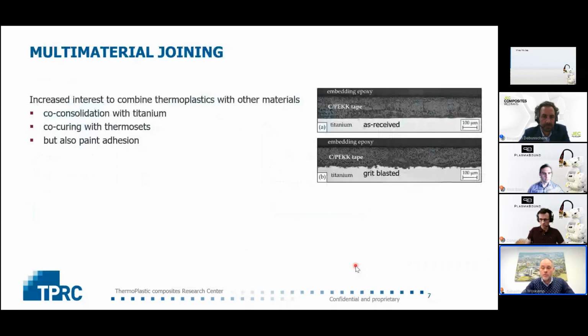So we have run 2 PhD projects already on the joining of thermoplastic composites to titanium, specifically carbon PEKK, through co-consolidation. So in one step, without a secondary, so an adhesive or intermediate layer, we join these 2 materials. And the performance really depends on the type of treatment. So surface treatment is very important here. We're currently investigating co-curing with thermosets. So since 1 year, we have a project in this field on our roadmap.